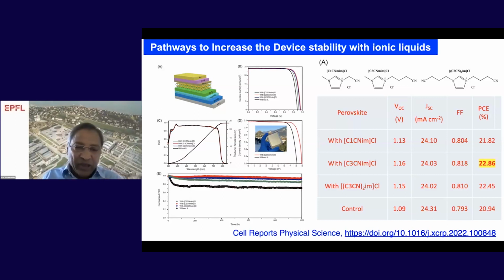So this way you form a nucleus when you have an ionic liquid in the composition of the perovskite solution: lead iodide, organic cation, and this ionic liquid. So it forms a nucleation, and the nucleation should grow into crystals. So that's the purpose of having these functionalized ionic liquids.